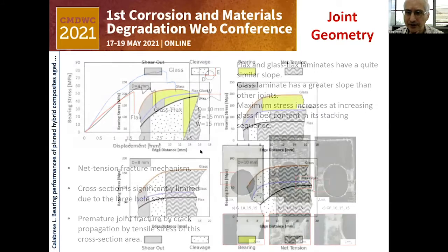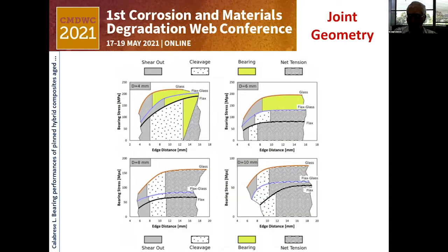Now, at this point, an approach was proposed to identify how the joint geometry influences the failure mechanism. Here, I summarized some results where we see that changing the edge distance and the diameters of the hole, we have different failure mechanisms. It's important to see that the net tension fracture was observed mainly for hybrid or for natural flax composite laminates. The reason is that for this type of fracture, the stacking sequence has a relevant role in the mechanical performance of the joint.